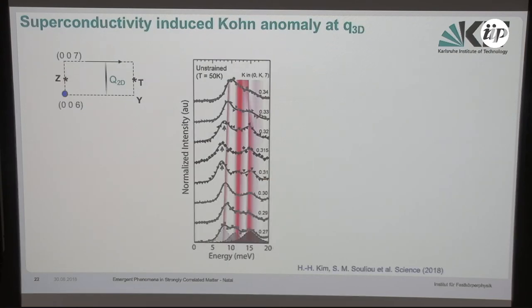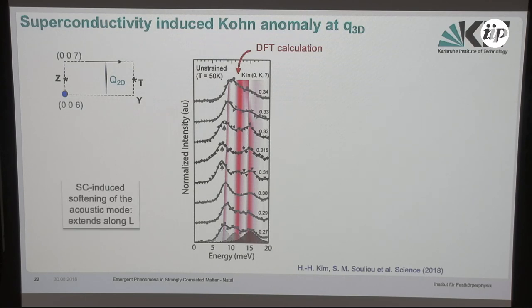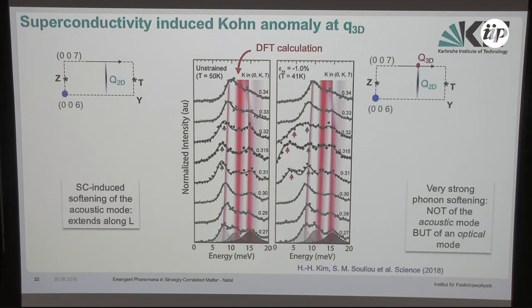And the icing on the cake is that because we did inelastic X-ray scattering, we can also look at the phonons. What we discovered doing the scan along this L equal 1 direction at the 3D wave vector is that the Kohn anomaly in the superconducting state that we had noticed earlier for the 2D charge density wave actually already exists. Here I compare the phonon spectrum with the ab initio calculation, and you see a deviation in that region at the 3D Q wave vector. And when I now apply strain, the acoustic mode that experienced this small anomaly falls back onto where it was supposed to disperse.